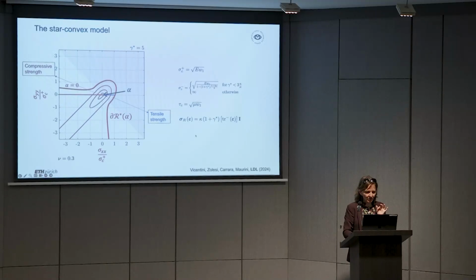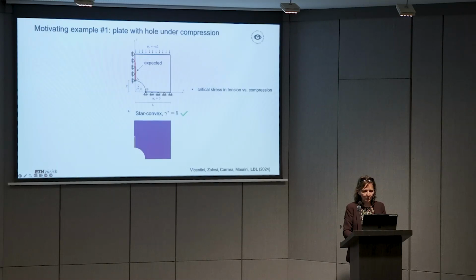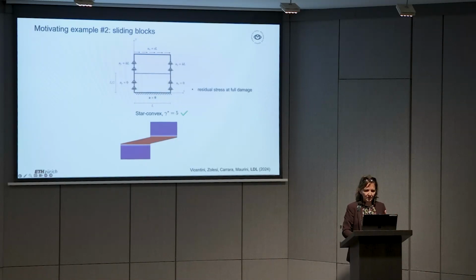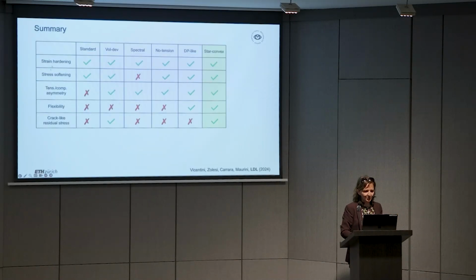So essentially this model, by adjusting the parameter, you can adjust the compressive strength. For some ranges of the parameter, you can even get infinitely large compressive strength if this is, let's say, a reasonable assumption for you. So if we go back to the examples I showed you, in the plate with hole example, we get a good behavior. In the shearing of the blocks, we get a good behavior. So if we go back to a table which summarizes all the requirements that I've been listing before, this model checks all the boxes.